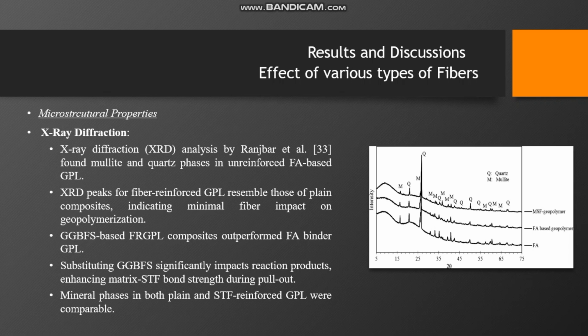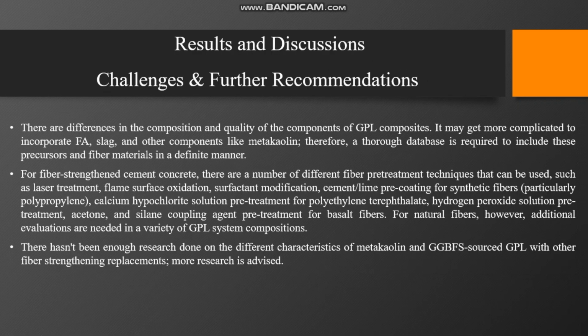Next, we have the X-ray diffraction. Using X-ray diffraction, Ranjbar et al. found the sourced mullite phases on the unreinforced paste geopolymer in addition to the crystalline phases of the quartz. The XRD, which stands for the X-ray diffraction, peaks for the fiber reinforced geopolymer resemble those of plain composites, indicating the minimal fiber impact on geopolymerization. The mineral phases in both plain and the synthetic fiber reinforced geopolymers were comparable.